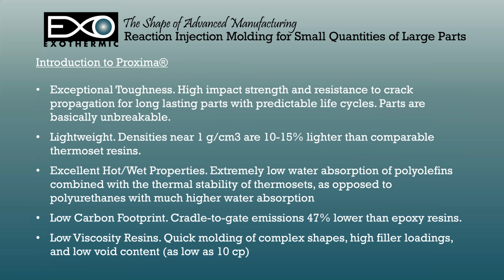It's also lightweight. Densities near 1 gram per cubic centimeter are 10 to 15% lighter than comparable thermoset resins. It has excellent hot-wet properties, extremely low water absorption of polyolefins combined with the thermal stability of thermosets, as opposed to polyurethanes with a much higher water absorption, and that is also a big advantage. Low carbon footprint: cradle-to-gate emissions are 47% lower than epoxy resins. And the resins are low viscosity, quick molding of complex shapes, high filler loadings, and low void content, possible with viscosity as low as 10 centipoise.